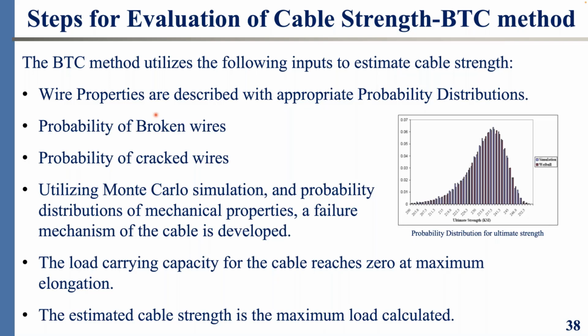If you see 5 or 6 wires during inspection, it doesn't mean that you have 5 or 6 wires in the entire cross section. Of course, remember, we see only about 10% of wires in the bridge cable when we do the inspection, and we do the probability of cracked wires based on the sample that we have taken and inspected under the microscope to identify the presence or lack thereof of pre-existing cracks.